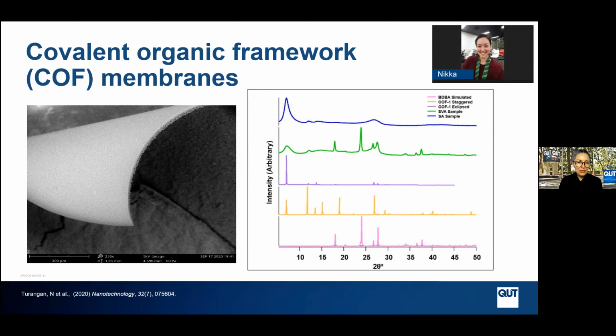So she's able to synthesize these membranes, which, as we show in the paper that I cite here, are chemically COF. There's a bit of, our conversion efficiency isn't 100%. It's quite interesting to work on this. When you're working on a bulk synthesis, you just wash away the stuff that you don't want. But when you make it into a membrane, you tend to lock it in. But these turn out to be really interesting from a bunch of different standpoints.